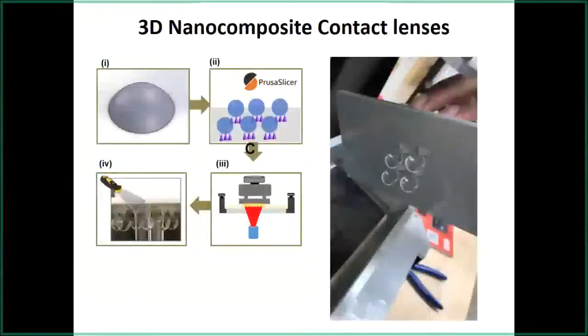Yes. So when the contact lenses on which we put our nanostructures, the ones with lasers, we actually characterized the surface very thoroughly, and the nanostructure was actually engraved into the surface. Because the surface was made absorbing with a dark material, after the ablation process, the ablation had left these trenches in the hydrogel surface.